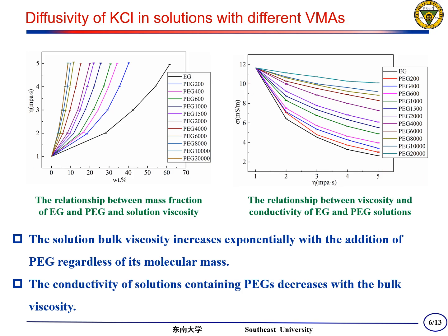It is also noticed that PEG with lower molecular mass exhibits higher efficiency in reducing the conductivity at given bulk viscosity. This phenomenon emphasizes the significance of molecular mass for reducing ion diffusion in solution.